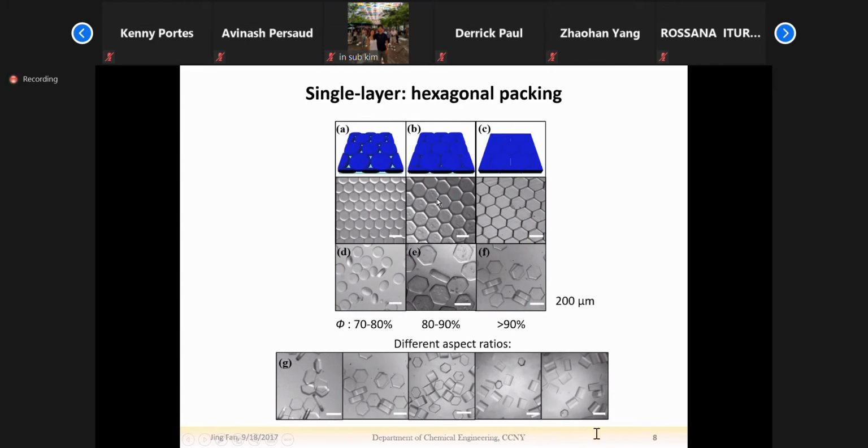If we further remove the continuous phase, these droplets become hexagon shaped, then we polymerize them, and they become hexagon discs. We can also control the thickness between the two plates to make the disc higher and higher, until we control the aspect ratio of the resultant hexagon disc or prism.